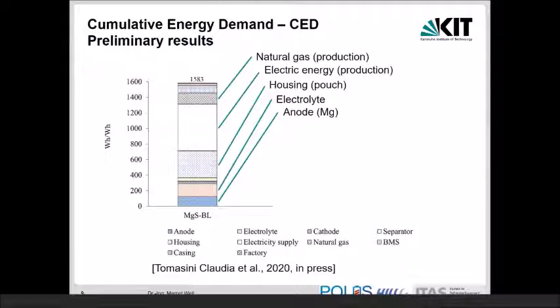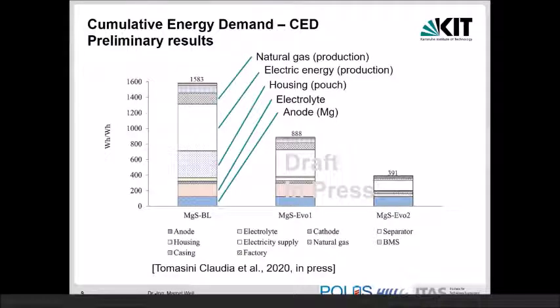And if you now compare this baseline scenario with the two other scenarios which I showed beforehand, you see that the impacts of the theoretical scenarios are significantly lower. For instance, the housing, which has a big contribution in the not optimized case, now has really little impact, and it's more reliable, I would say. And even more so with the next evolution, with the separator now adjusted to normal values, which looks more reasonable, and also now with the saved electrolyte. So that could be the direction of improvement of such a cell, even if it's just on a theoretical level.